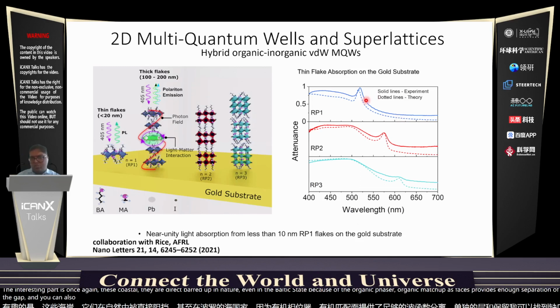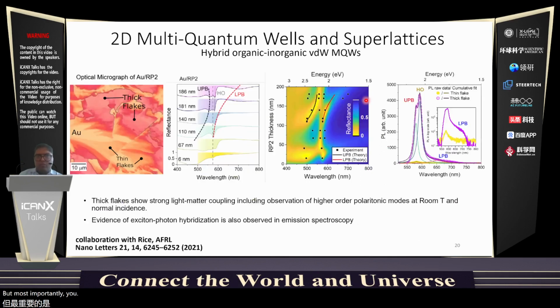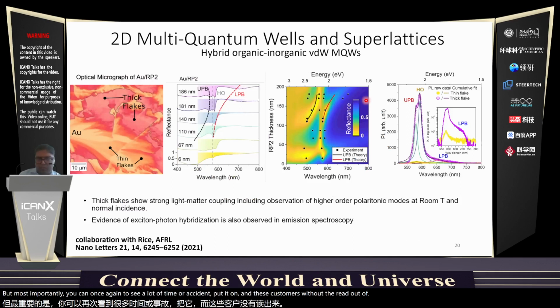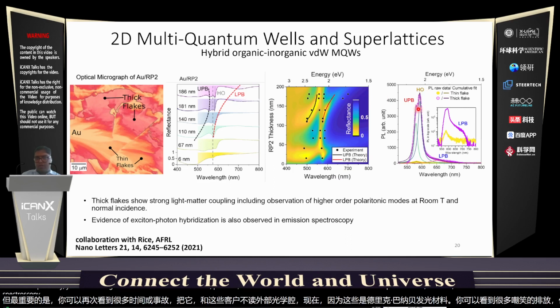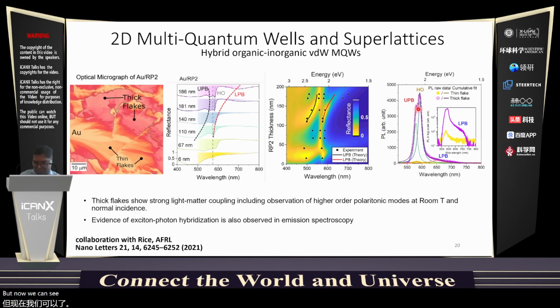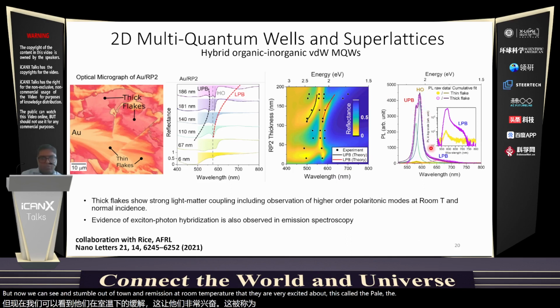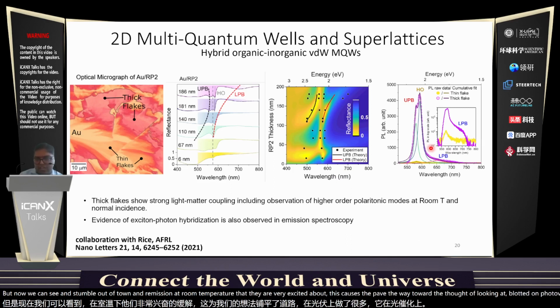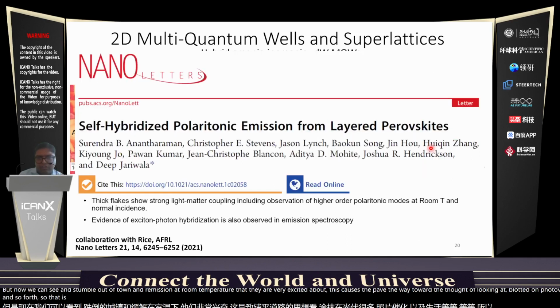And you can also trap light very easily in them for very small thicknesses. But most importantly, you can once again see polaritons or exciton polaritons in these crystals without the need of external optical cavities. And now, because these are direct band gap emitting materials, you can actually see polaritons in the emission spectroscopy at room temperature. So now we can see exciton polaritons under emission at room temperature, and we're very excited about this because this paves the way towards looking at polariton photovoltaics or polariton photocatalysis, as well as lasing and so on and so forth. So that is some of the areas we are looking at. This again was published 3 or 4 months ago in Nano Letters.